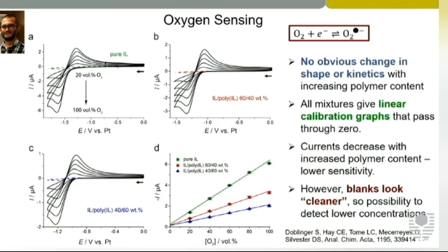So this is oxygen reduction. I've said before that you reduce oxygen to superoxide, so that's the reduction peak, and then this is the superoxide oxidation peak. What you can see here is the calibration graph. As you add more polyionic liquid, obviously you're making it more solid-like, so you're going to reduce your sensitivity, or the gradient of the calibration graph.